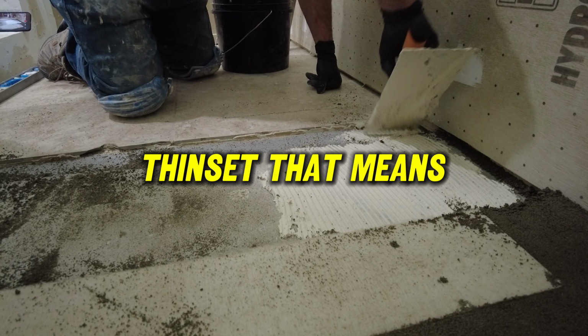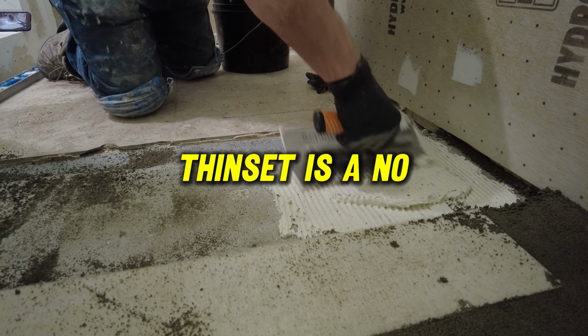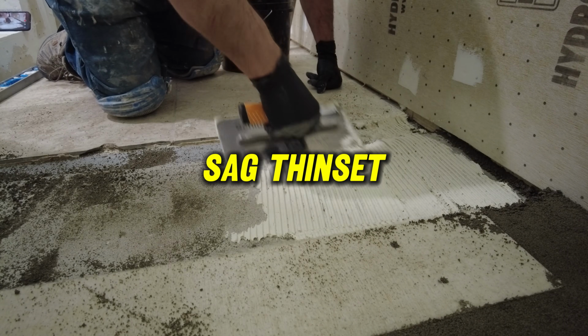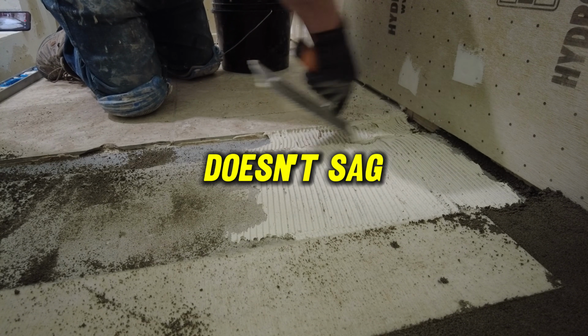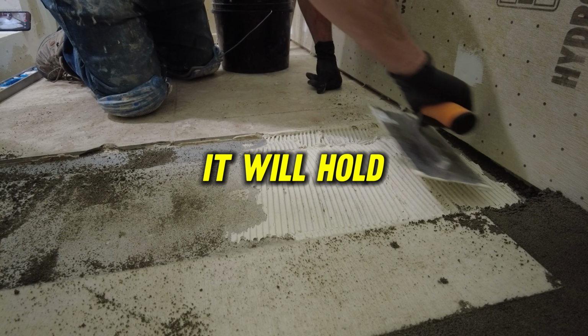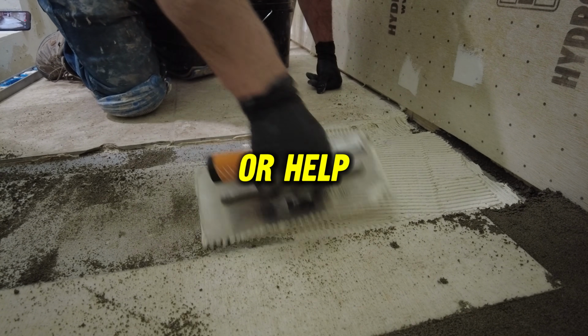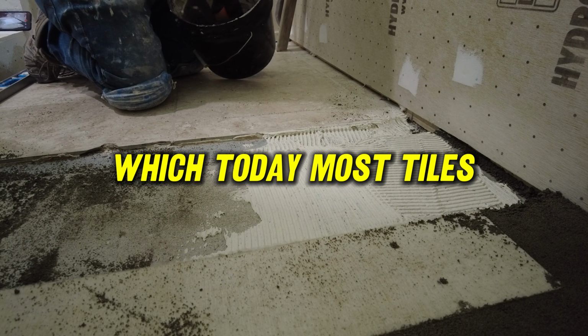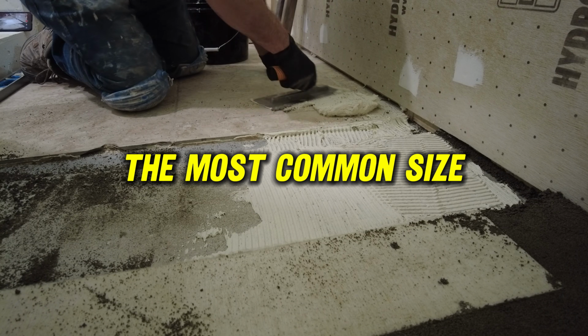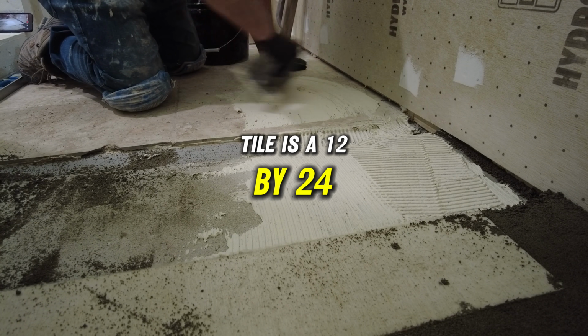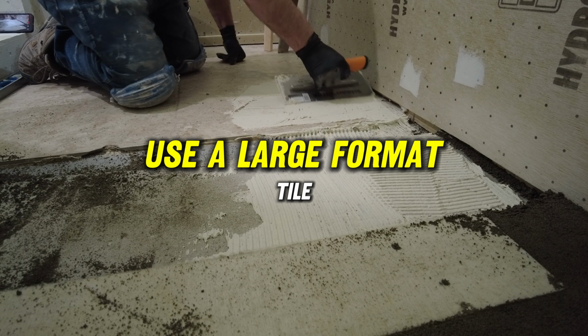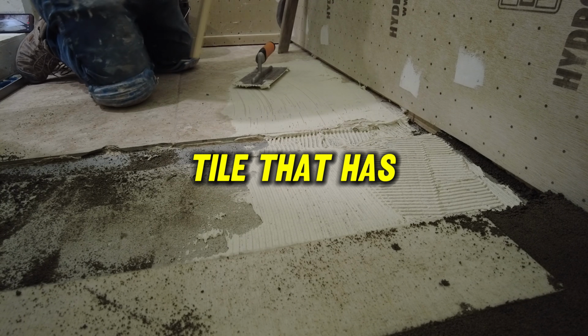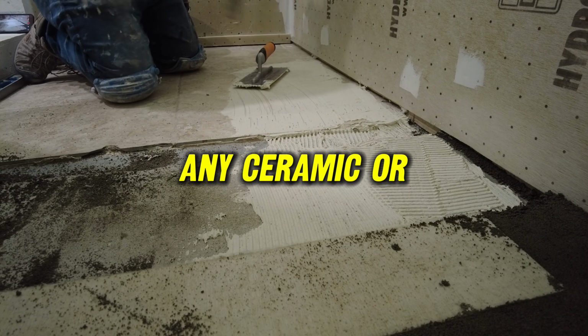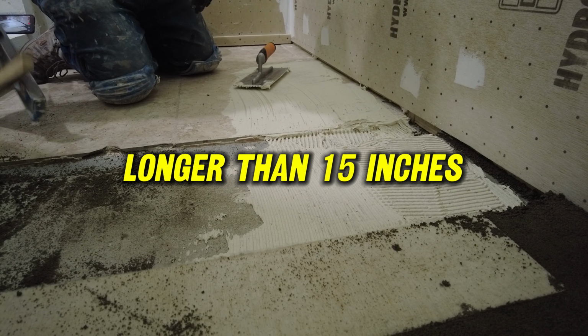A118.15T Thinset. That means the Thinset is a no-sag Thinset. The T stands for thixotropic, which means that it doesn't sag, it'll hold the tile up or help keep it from sliding down the wall if it's on a vertical surface. If you're going to be installing a large format tile, which today most tiles are pretty big, the most common size tile is a 12 by 24. So if you're going to be using a large format tile, and just quickly, the definition of a large format tile is any ceramic or porcelain tile that has one side longer than 15 inches.